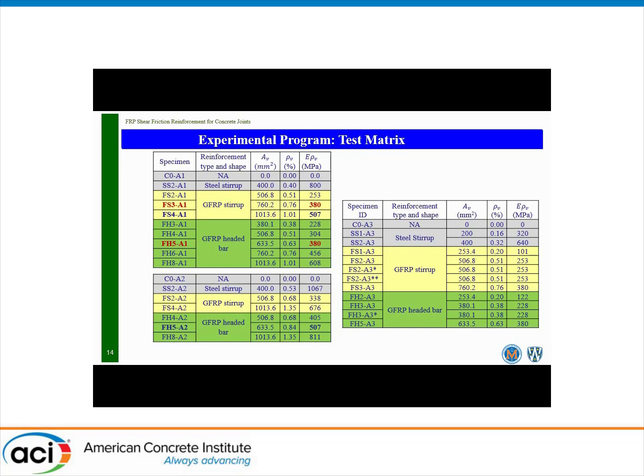Instead of 250 by 500, we went to 250 by 300 to generate a higher reinforcement ratio. Again, we have a plain unreinforced specimen, a steel specimen with 2 stirrups, GFRP stirrups with 2 and 4 stirrups, and headed bars with 4, 5, and 8 headed bars.